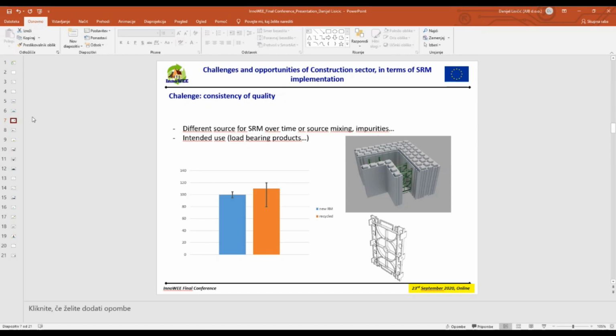Although the average tensile strength was even a bit higher, we chose to produce brackets from virgin polypropylene. During pouring of concrete on a construction site, we cannot afford that some brackets break, because we could endanger workers' lives. So it's also the intended use that could make a difference. And such a broad result range was not acceptable for us.